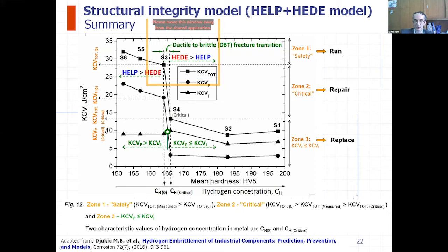The first one is the safety zone, which means a run decision, where the mechanical properties are still not affected by activation of the HEDE mechanism. We have a HELP mechanism, but a very slight drop of ductility and impact strength in this case. The repair area corresponds with the reaching of the critical hydrogen concentration and the sharp drop of total impact strength and the crack propagation component of impact strength, which then becomes lower than the crack initiation component, which presents zone 3. This is connected with the immediate replace decision of the components, since the crack propagation component is lower than the crack initiation component, and failure due to hydrogen could occur very easily and very frequently.